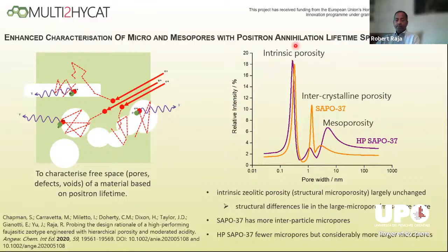For example, in the intrinsic porosity, we know that our hierarchical material has a porosity which is intrinsic to the microporous system, but then it has this well-defined secondary porosity, which is really in the close vicinity to the microporous architecture. So the peaks you see there are attributed to the voids in the micropore regime, which is interconnected to this mesopore regime, as indicated by the tau value decays of this particular structure. Interestingly, the hierarchical system has much fewer micropores, but considerably larger mesopores, which could be used for mass transport. So this is the background in terms of how we made these hierarchical materials.